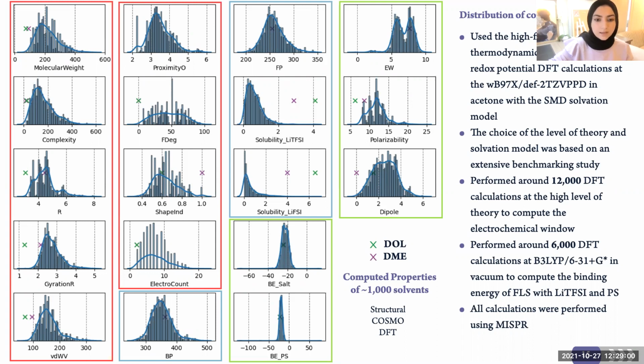As for the binding energy, we used a lower level of theory because we found that it was enough to reproduce accurate trends, because we are not interested in the exact quantitative data for the binding energy, but rather the qualitative trends in the data. And we performed around 6,000 DFT jobs for the binding energy with both the solvent, the salt, and the polysulfide.